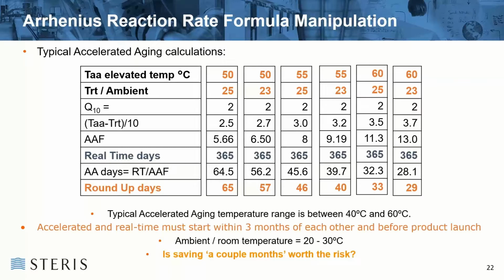The accelerated aging and the real-time aging must, or should, start within 3 months of each other. So you're achieving a relative alignment with the product and the packaging that's in use at that time. So you're using the same lots, the same batches of product, the same batches of packaging. However, what you must take into account is saving this couple of months shown in the tables above. Is that worth the risk? And you have to define what that risk may be.